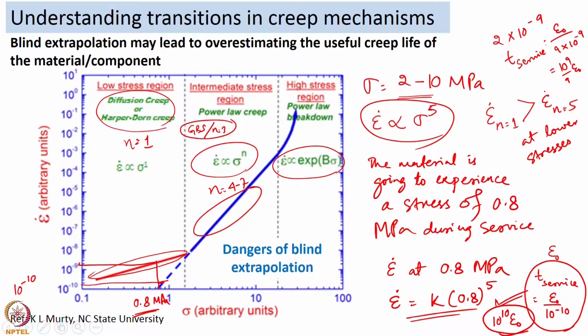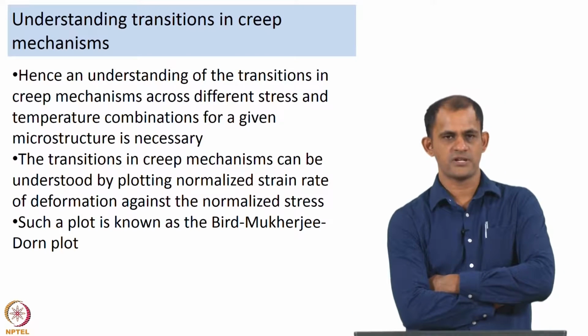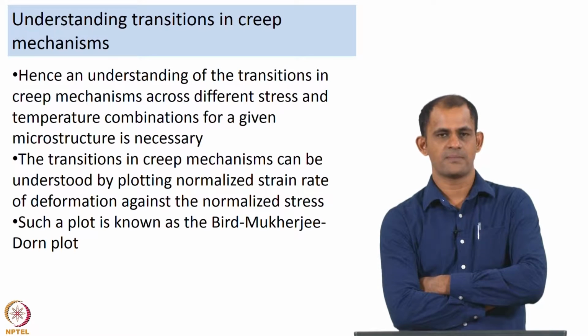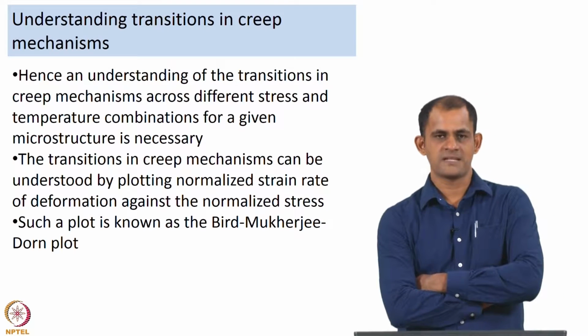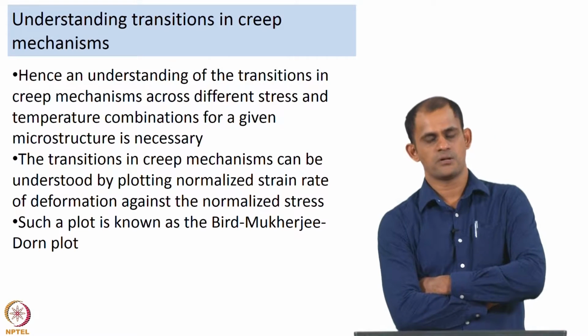from just blind extrapolation. So, the whole objective of this slide is to tell you that you should understand the deformation behavior of the material over different stress and temperature ranges and not rely on blind extrapolation, because you might significantly overestimate the useful creep life of your material by relying only on blind extrapolations. Hence, an understanding of the transitions in creep mechanisms across different stress and temperature combinations for a given microstructure is necessary.